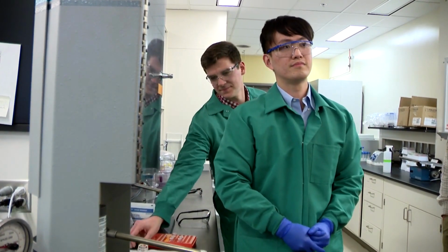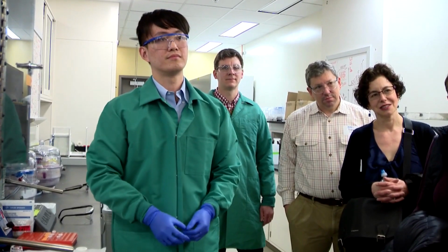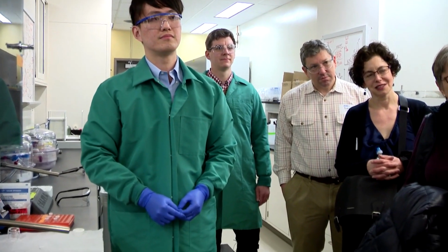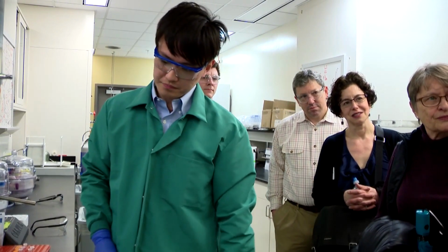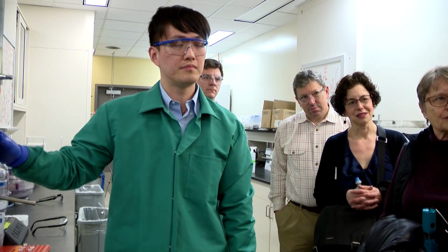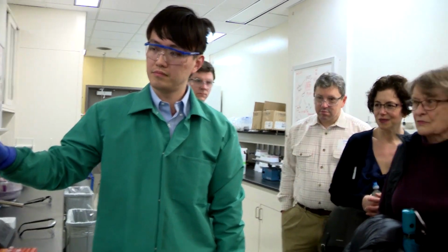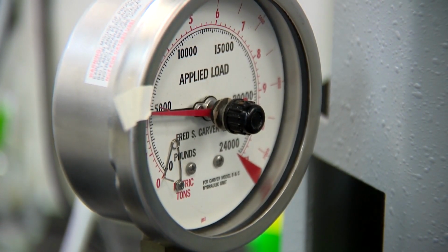The idea is that they would go into the omentum, because you have lots of space there, and it also has some natural wound healing properties. It goes in through a laparoscopic procedure, so it's not terribly invasive either. We put them under pressure, 5K pounds for 30 seconds, to press them together. As I said, they're a mix of PLG particles and table salt.